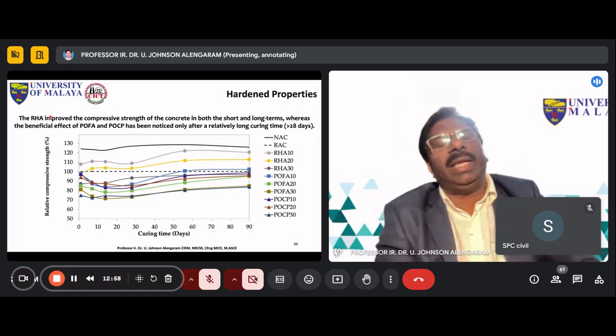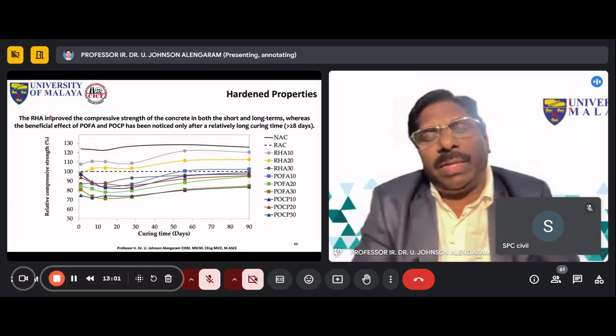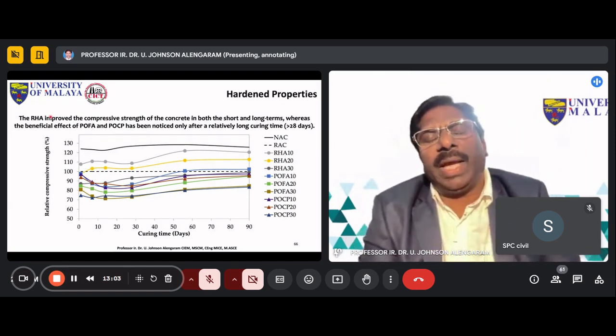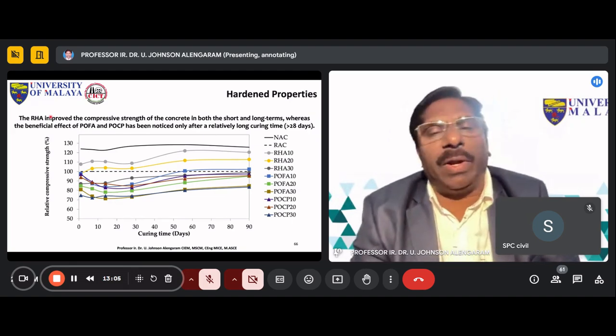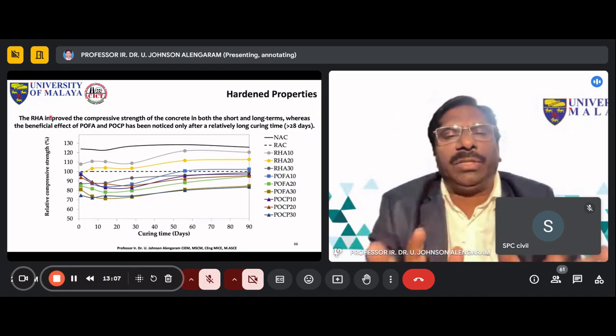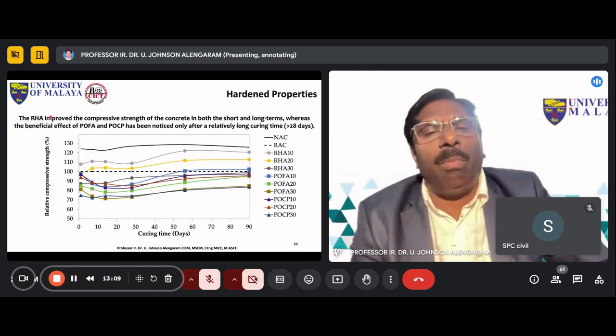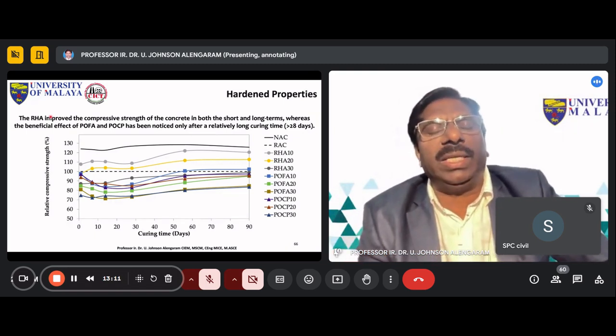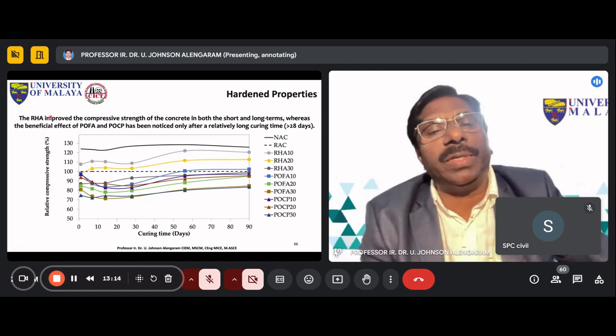However, for the relative compressive strength, we can see the RHA has improved the compressive strength of concrete, because of the silica. When we mix cement with water, it produces calcium silicate hydrate and calcium hydroxide compounds, whereas the calcium silicate hydrate is a strength-producing compound. The calcium hydroxide is just standing there without contributing towards the strength.